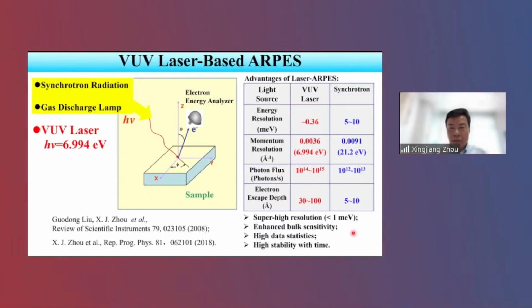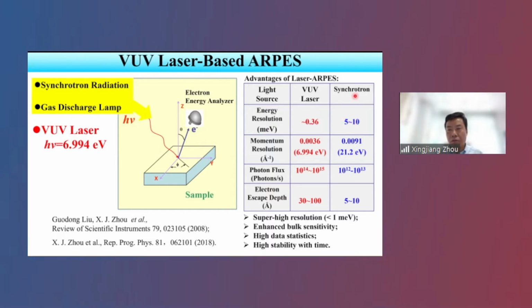As you know, ARPES, angle-resolved photoemission, is a very powerful tool to study high-temperature superconductors and other quantum materials. Usually, people use synchrotron radiation as a light source to do ARPES. But in my lab, we are using a vacuum ultraviolet laser as a light source, so usually the photon energy is about 7 eV. By using laser ARPES, I think it has many advantages. Most importantly, the energy resolution can be much improved from the usual 5 to 10 millivolt in synchrotron ARPES to better than 1 millivolt in our laser ARPES.